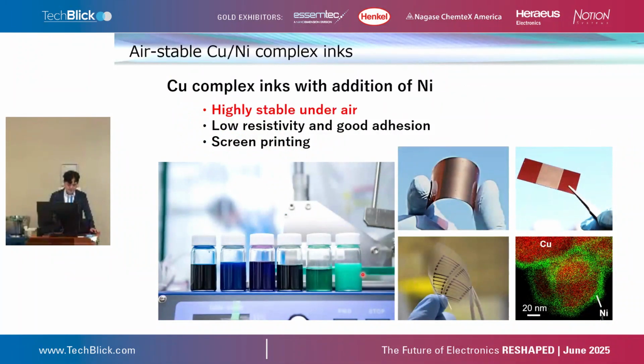And so my complex is, as the first speaker spoke about, the kind of ionic state and reactive type inks. And in this picture, the left three inks are the copper complex, and the right three inks are the nickel complex. And in this work, we actually mix them together to improve the oxidation stability under air. And after printing the copper nickel mixed ink onto the substrate, if we increase the temperature, the reduction of the metal ion will start. And then we can obtain pure metallic films as the result of the thermal decomposition process.